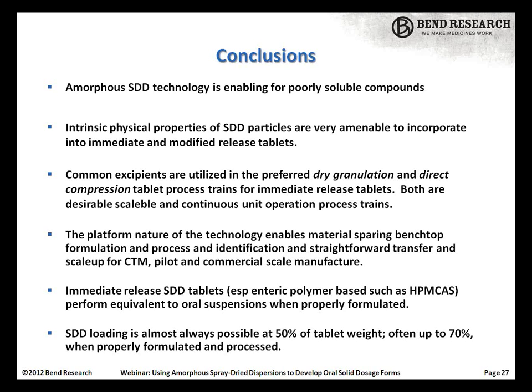I would say, for a 50% loaded SDD, 250 milligrams in a dosage unit is our typical target here. If it's down to 25, our target might be around 150 milligrams. If we're fortunate enough that the properties are such that we can go above, we can approach up to 400 milligrams in a single tablet in some cases.